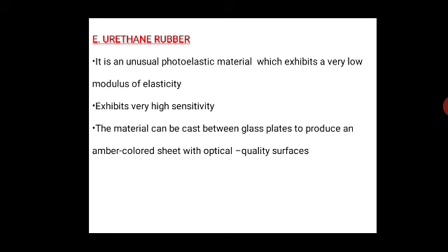The material is particularly suited for demonstration models only, and loads applied by hand are sufficient to produce well-defined fringe patterns. In the absence of time edge effects, the models can be stored for years. Along with this, the material is so sensitive that it can be used to study body force problems, and fringe multiplication techniques are employed with thick models.